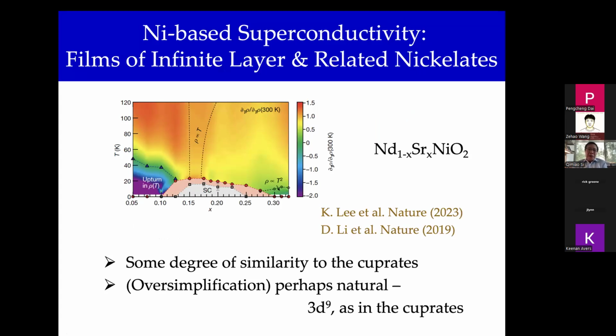Nickel-based superconductivity was a course of long slog, and so the heroic effort of Harold Hwang and others in the community, who realized superconductivity in the films of infinite layer nickelates. And this is a typical phase diagram of this infinite layer nickelate. Tc is somewhere about 15 to 20 Kelvin, and it was discovered at a time when the field had reached a bit of a lull. The color plot showcases the different regimes, including the characteristic dome of superconductivity. x here marks the usual doping through substitution.